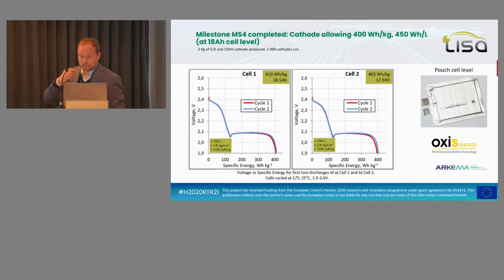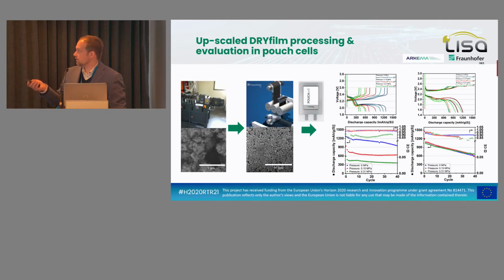This is a generation that we did in November 2020. So this is almost a 20 ampere hour cell level, giving more than 400 watt hour per kilo and approximately 450 watt hour per liter. So yeah, pretty in line with what you can find in the state of the art.